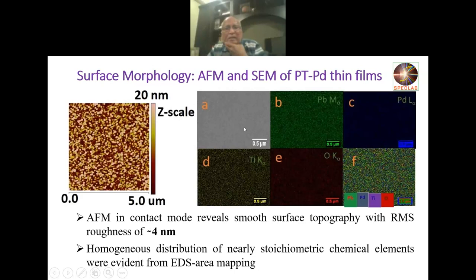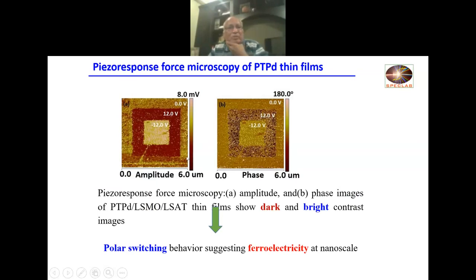For surface morphology, again, we checked to see if this material is uniformly distributed. You can clearly see all of the elements are very uniformly occurring over the region that we have investigated, and the surface roughness was something like 4 nanometers. We also did piezo force microscopy of these thin films. You can see there is a good switching, something like at 12 volts in both cases, phase as well as amplitude. That clearly shows that there is polar switching in these materials, and that means there is ferroelectricity at nanoscale.